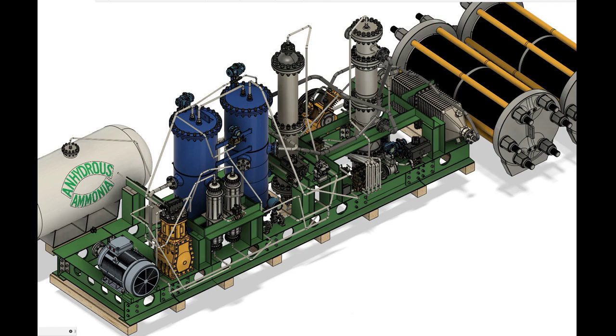It makes no sense whatsoever to custom fabricate fancy components when these high-pressure stainless components can be readily used in low-flow rate plants. For a small reactor weighing only 1/4 of a ton, more expensive alloys such as stainless steel or even Inconel can be used, without much of a concern for cost, as the relative contribution of reactor mass is trivial. The use of these high-nickel chromium alloys allows the plant to be used in corrosive environments, although this should not be a concern since the sensitive components can be hermetically sealed from the elements in the ISO container.